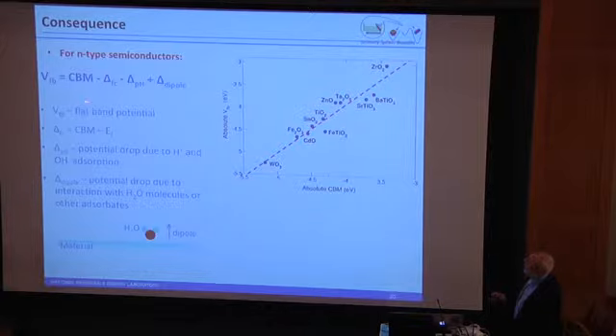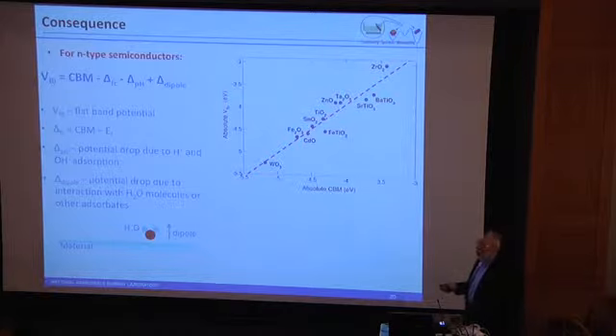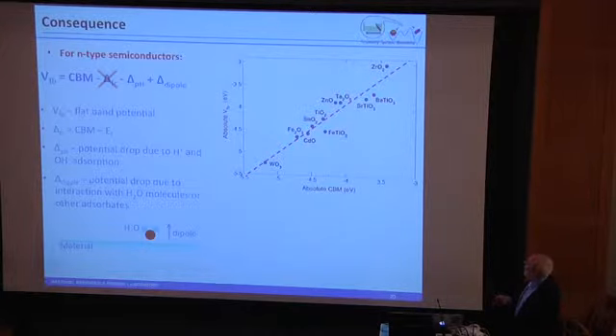So what we'd like to do is understand the factors that are important. The flat band potential is clearly one of them. The conduction band maximum is another. Then there's the difference between the conduction band and the Fermi level, which is delta FC. There's a pH-dependent term, which I said is this point of zero charge. And then there's a dipole factor, which is due to the interaction of the water molecules on the surface, which is essentially the Helmholtz layer. Now, if we take this curve, we can basically throw this out. It's a very small term. We can throw out the pH term if we're at the point of zero charge. And then we have to look at the dipole.